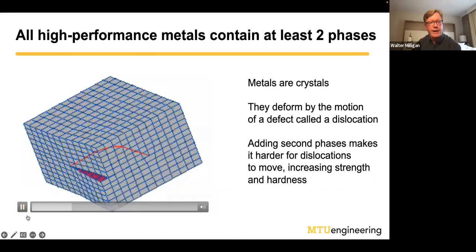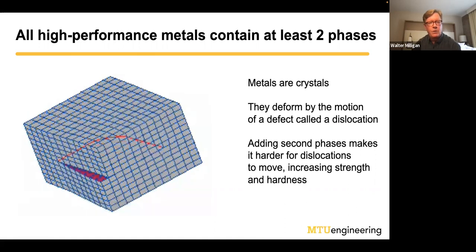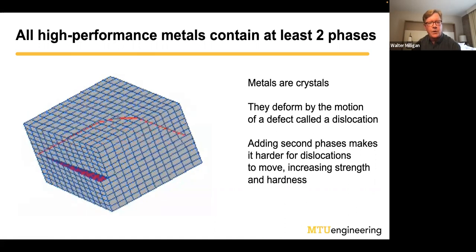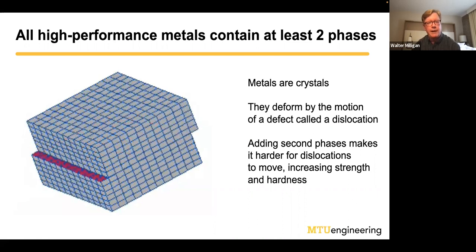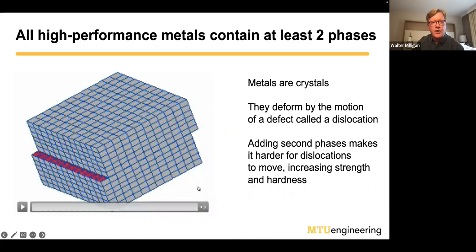If you watch how that red line moves through this crystal, what you'll see is at the end, we had a crystal that started out as a cube, and now it looks like it's got an offset there. If you did that on multiple parallel planes, you could get enough deformation that you could measure. For example, if you've got a chef knife, nice and sharp, and then you cut into a bone or hit your cutting board a little too hard and it gets dull, what's happened is that billions of these defects have moved. That's why it changed shape from sharp to dull.